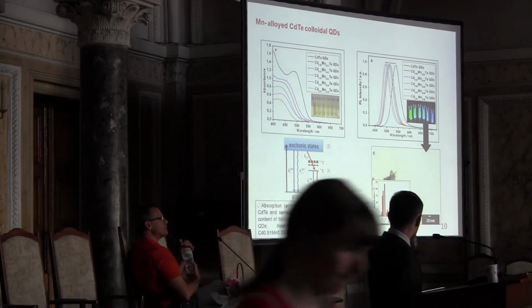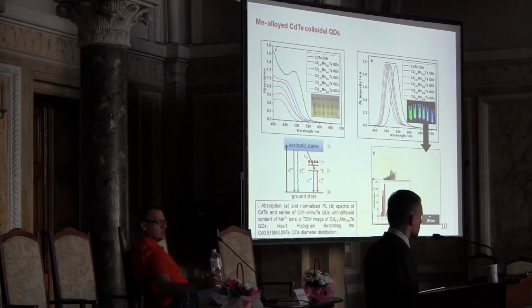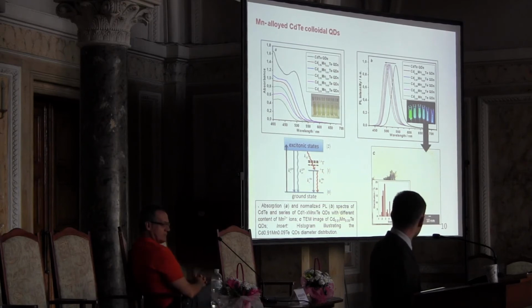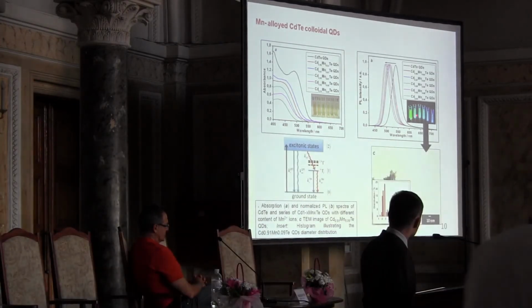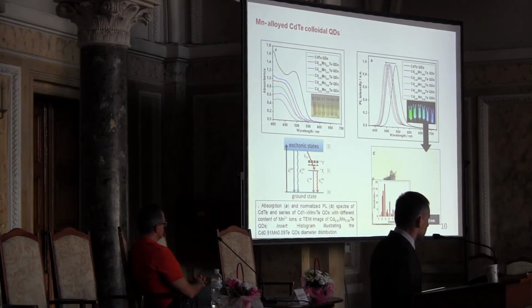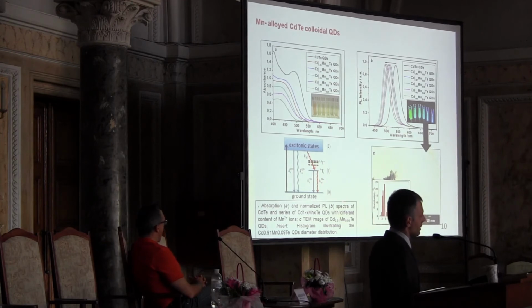And it's interesting because normally you expect that manganese in A2B6 semiconductors would emit in the red region, which corresponds to this kind of transition. But in this case, we observed an interesting point, because we observed basically only excitonic luminescence. And what people say is that it was shown in some cases for cadmium selenide quantum dots doped with manganese that in those systems a kind of reverse energy and electron transfer occurs. So if you have quite a lot of those electrons here, they can go back thermally, because we are measuring at room temperature, and you observe only this kind of transition because the difference here is not very high.